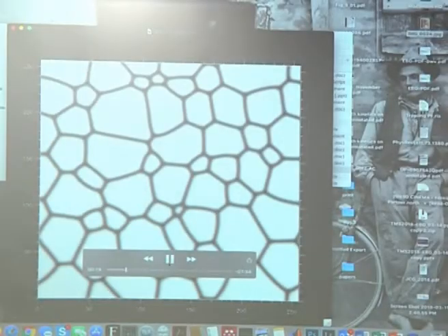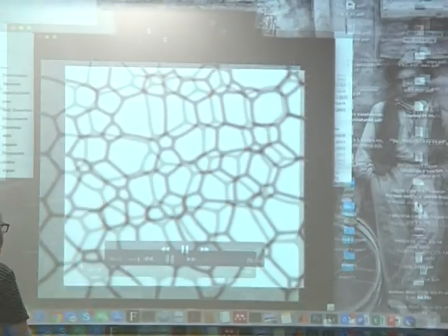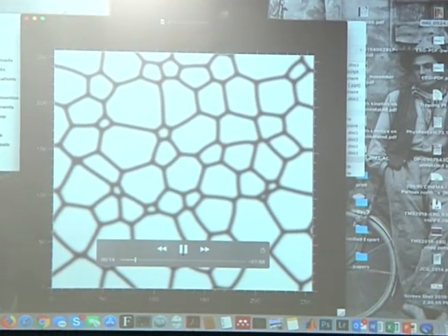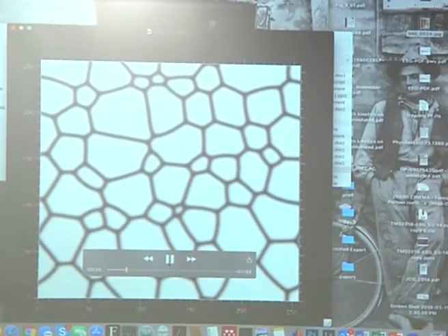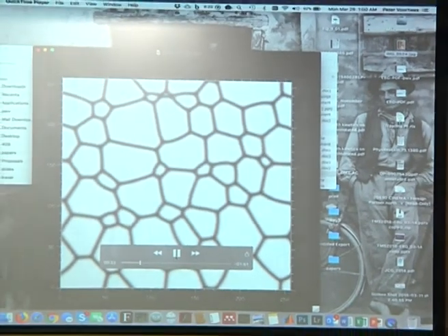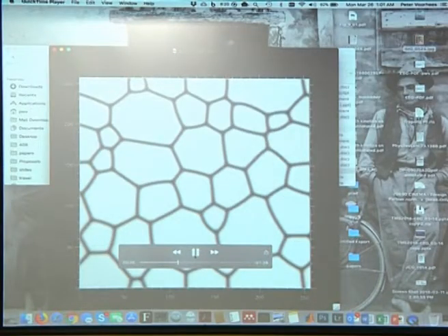And so this is a system where you have n grains, and you start off with random noise, and the system goes to the wells and creates the grain boundaries. And the grain energies, and you can see that it looks very much like grain growth. Small grains disappear. You have instabilities with quadruple junctions. They disappear. And you get classical looking, very classical looking grain structures.